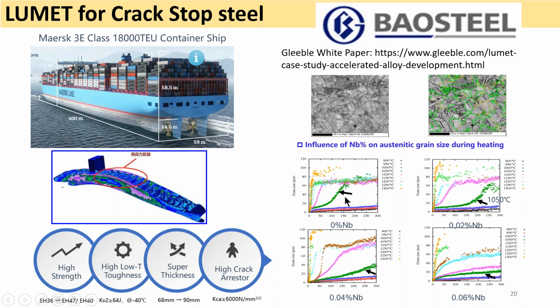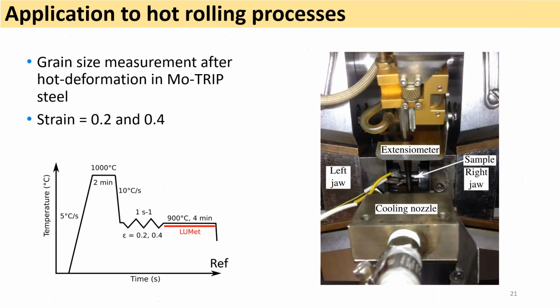So you can see that as they increase the niobium content, the abnormal grain growth occurring at this temperature is slowly pushed towards later times, to the moment where it just vanishes completely and abnormal grain growth is avoided in this case. So that's an interesting case study in which LUMet was used for very applicable industrial studies.